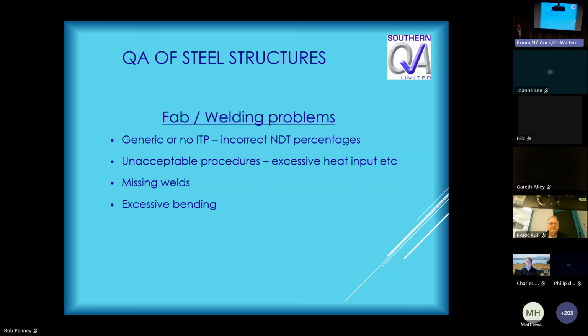So the sort of things that can cause that: generic ITPs, no ITP, maybe no inspection done, or the incorrect percentage, or the wrong method, unacceptable procedures, excessive heat input. Excessive heat input on stainless is particularly damaging. Missing welds. In some of the cases with that silo, the weld was almost missing because it was fused to the cylinder but not fused to the top of the skirt, which is a bit thicker and harder to melt